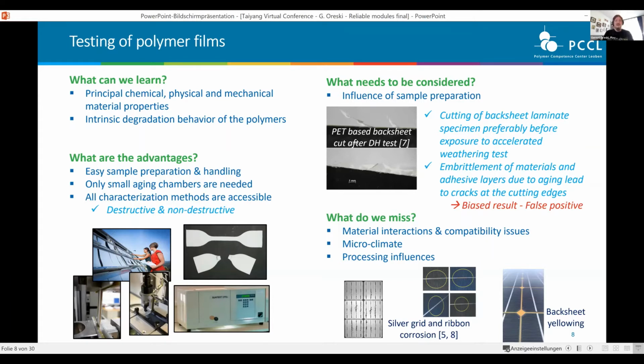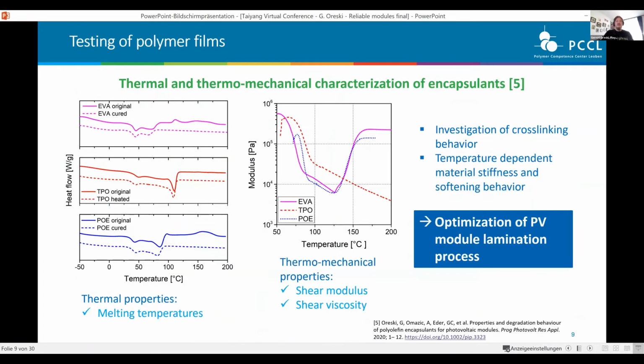So what do we miss when we just do testing of polymer films? We miss all kinds of material interactions and compatibility issues. Actually, we miss the microclimate of a PV module, and we miss all the processing influence coming from lamination. So we don't see corrosion effects. We don't see yellowing effects, for example.